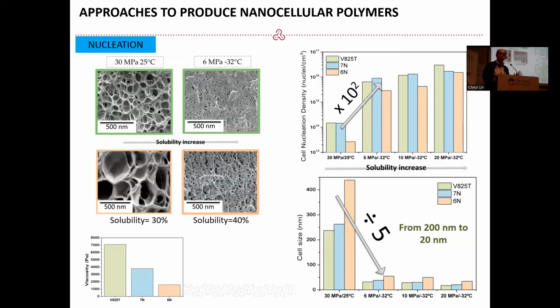Very simple. Another option is reducing temperature. By reducing temperature, we increase solubility. So here you have 30 MPa, 25 degrees C, 200 nanometers. 6 MPa, minus 32 degrees C, you have 20 nanometers. So by reducing temperature, you increase solubility, and then you have nanocells again. Also a very simple approach, but you dissolve the gas at minus 30 degrees C. The diffusivity is so small that you need many hours. So the process is, let's say, not viable from a production perspective.